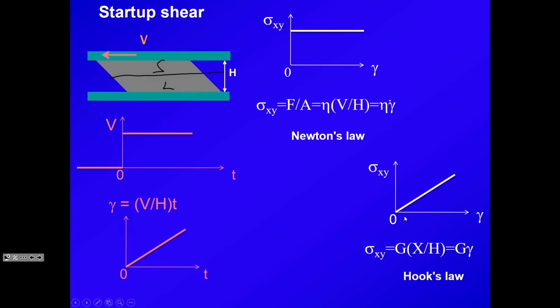In fact, the problem is exactly the opposite. You can only get the viscosity of this material if you start to make a measurement on a time scale longer than tau. But not at the beginning.